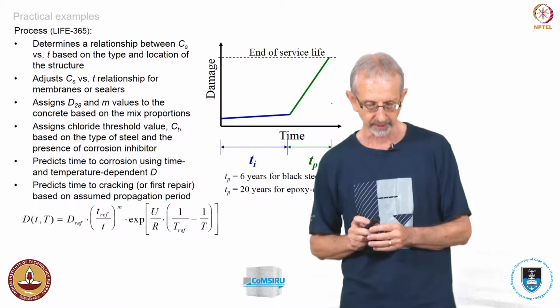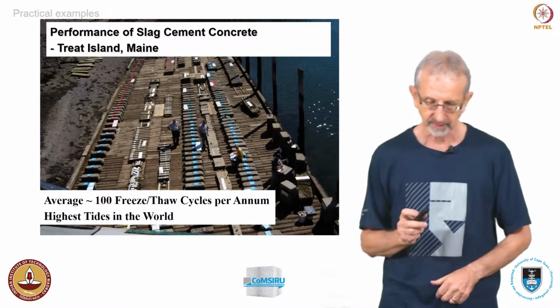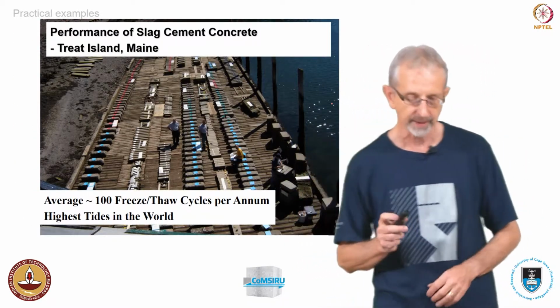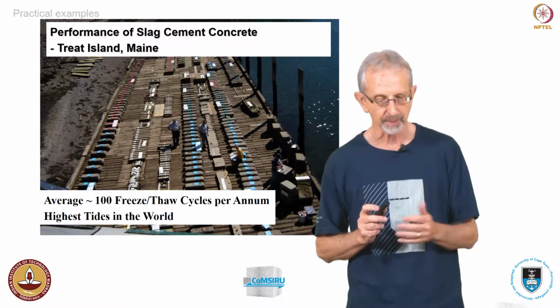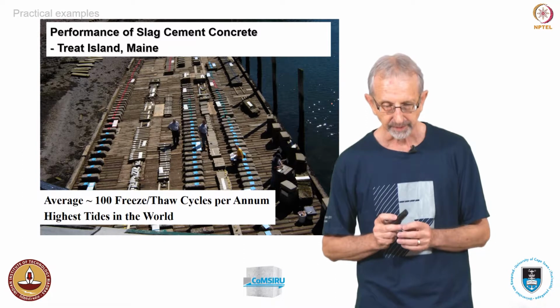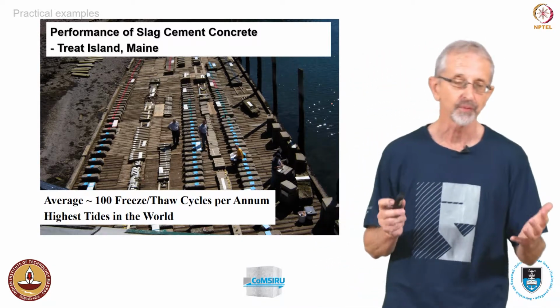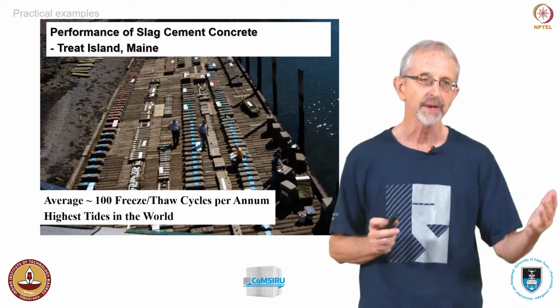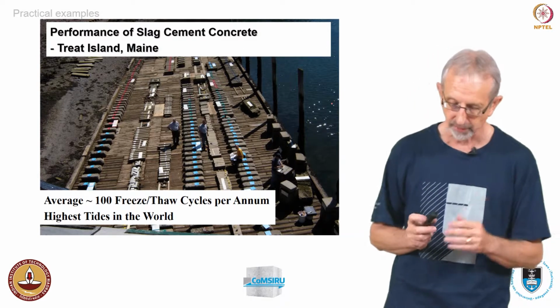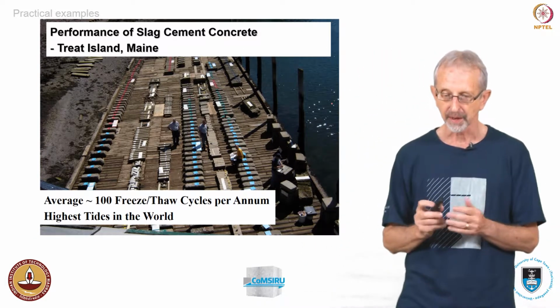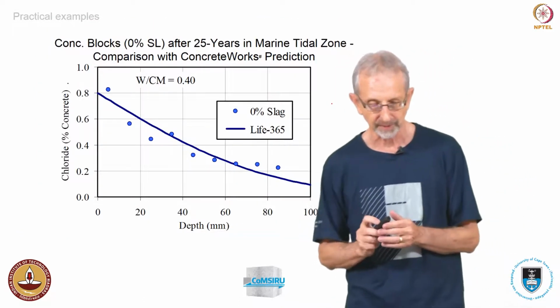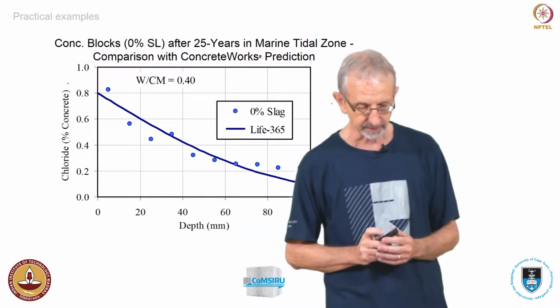So that's what the model does. And then they had this site at Treat Island in Maine, where they have exposed concrete for long periods of time, and they looked at the performance of slag concrete and saw whether the measured chloride ingress that they were able to actually go and measure was in any way represented by the model. And, well, yes, it was pretty well.